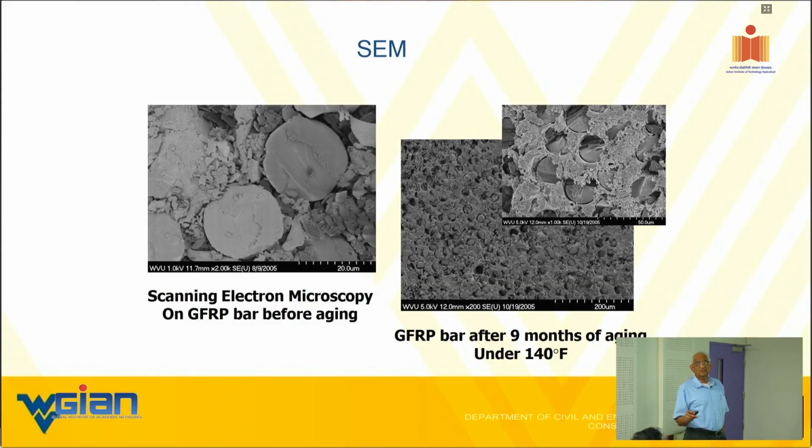Again, stiffness is not a primary issue because it doesn't get as much affected. If you look at the code, I'll talk about it, actually we only suggested a 5% reduction in stiffness, 15% reduction in strength.